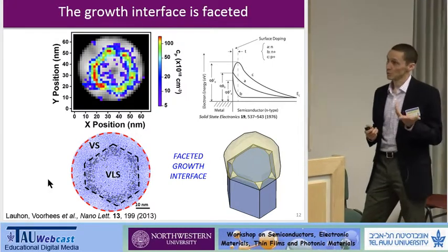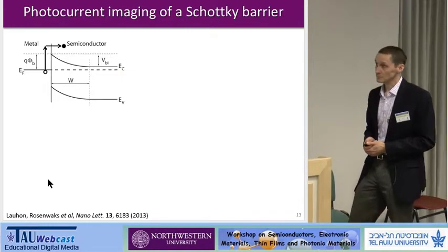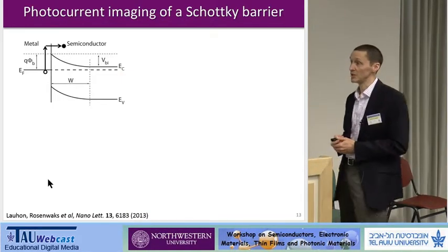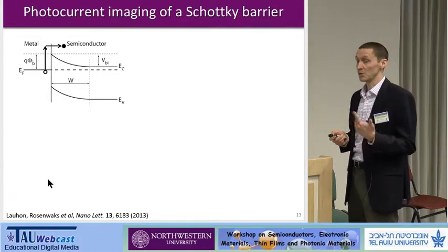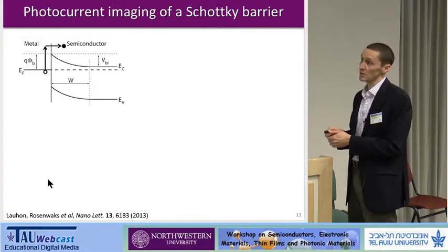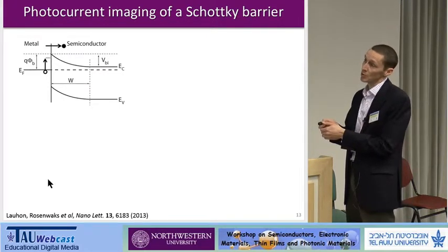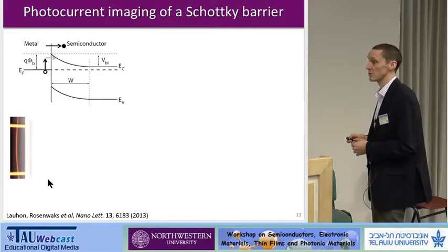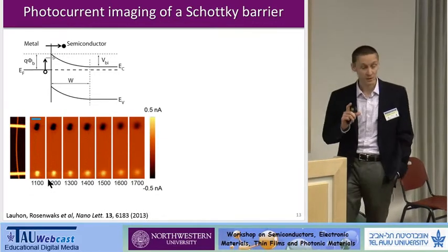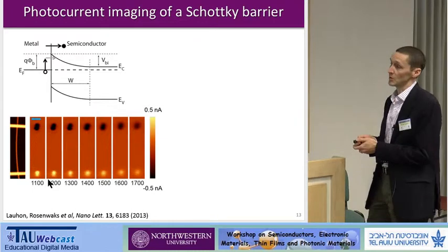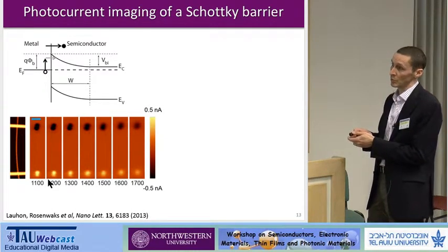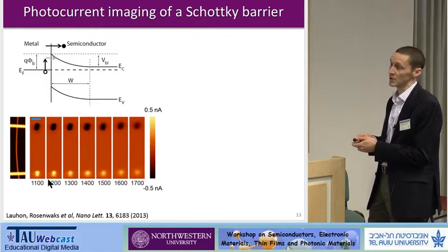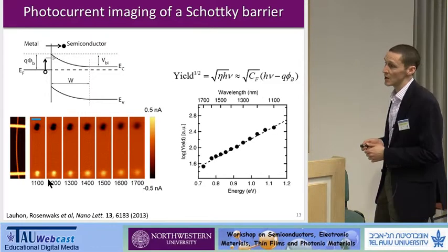So to explore what was going on in nanowires, we turn to this photocurrent imaging technique again, now going below the band gap and going into the infrared, where you probe electrons that are excited from a metal contact over that Schottky barrier. So this is a sequence of photocurrent images now focused on the contact regions as we go to longer wavelength, or lower energy photons. You see that current is fading.